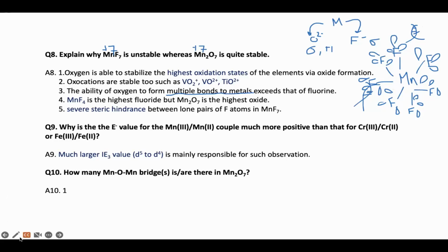The next question is, why is the E° value of the Mn3+/Mn2+ couple much more positive than that for the Cr3+/Cr2+ or the Fe3+/Fe2+ couple? In this case, the much larger IE3 value is the main reason for such an observation. You can see the Mn3+/Mn2+ couple E0 value. If we have to go from Mn2+ to Mn3+, Mn2+ is d5 and Mn3+ is d4. So the d5 to d4 transition will be very poor, because we have to break the half-filled stable configuration and go to a less stable d4 configuration. That is actually not in favor of the Mn2+/Mn3+ couple.